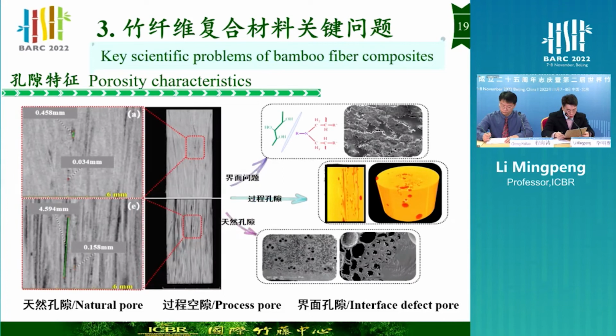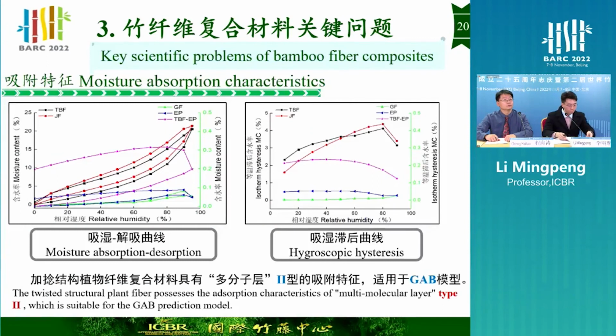There are three kinds of pores in bamboo fiber composites. That is, natural pores, process pores, and interface pores. The existence of pores will affect the properties of the composite. Meanwhile, in order to develop the interfacial compatibilizer, hygroscopicity is also another problem to be solved for the bamboo fiber composite. The tested bamboo fiber composite has the hygroscopic characteristics of multi-molecular layer adsorption, which is suitable for the GAB model.